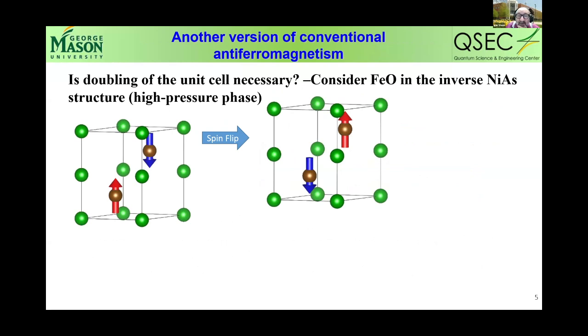Consider iron oxide in its high pressure phase, which is also called the inverse nickel arsenide structure. It's a hexagonal structure where non-magnetic atoms form just a simple hexagonal lattice, and magnetic atoms are these two. So there are two iron atoms in this case in the unit cell. And if you flip spins, you can clearly see that the structure is different, but it's symmetry equivalent.